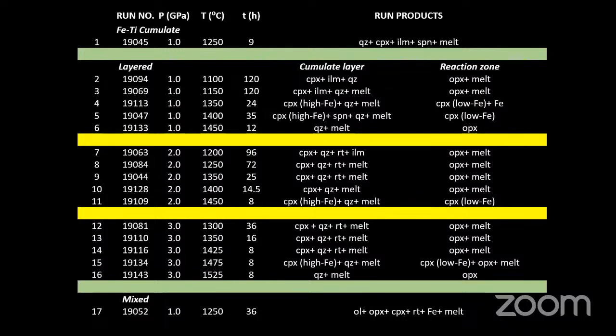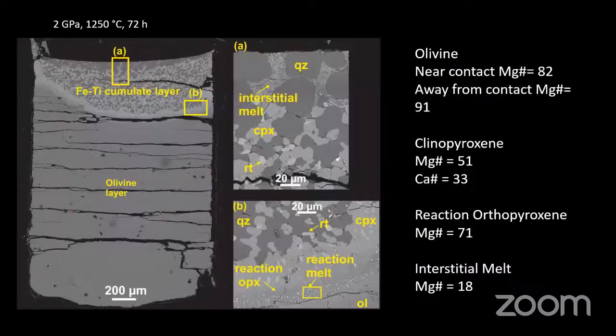But overall, in the subsolidus phase, we get clinopyroxene, quartz, and ilmenite or rutile in the FeTi-rich cumulate layer. There is a reaction zone that lies under this layer, which comprises orthopyroxene, reaction orthopyroxene, and reaction melt. And beyond that, there is the olivine layer, as we can see in this next picture. This is the construction of the experimental capsule, basically. Here we have about 80% olivine, and here is the reaction layer, and here is the FeTi cumulate layer.